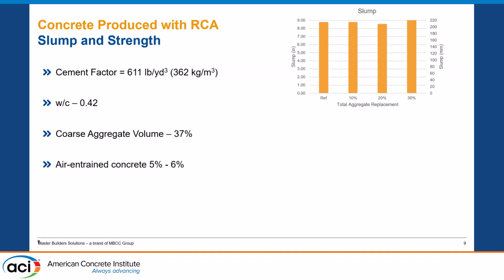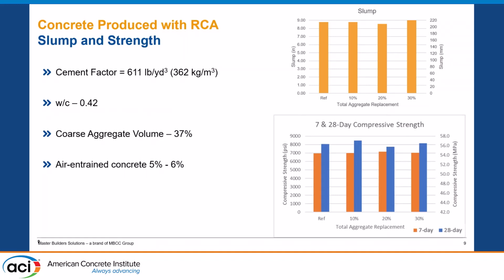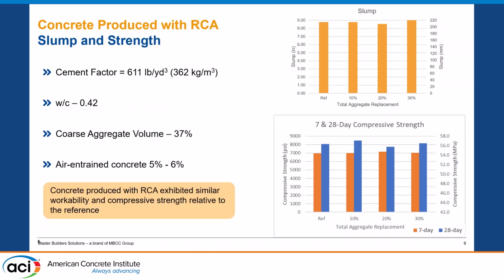In terms of workability, what we can see is that workability ends up being basically the same. In some cases, in some mixes, what we saw was a very, very slight increase in the water reducer demand, but in most cases, it was not noticeable. So here you can see that. When we go into the strengths, what we see is also the same thing. The strengths of the reference, as well as with 10, 20, 30% replacement of the coarse aggregate with the RCA, they are very comparable in all cases. So, conclusion is that concrete produced with this type of RCA exhibits similar workability and compressive strength relative to the reference.